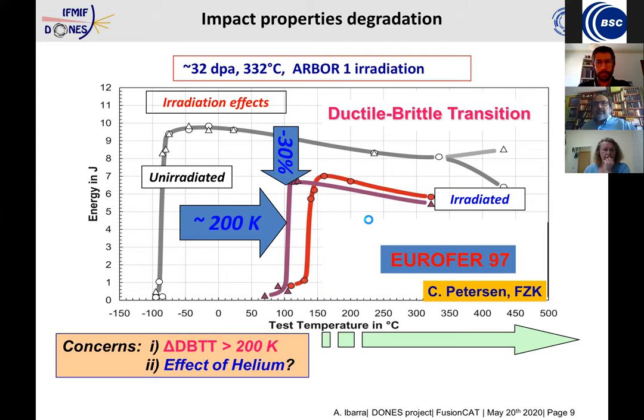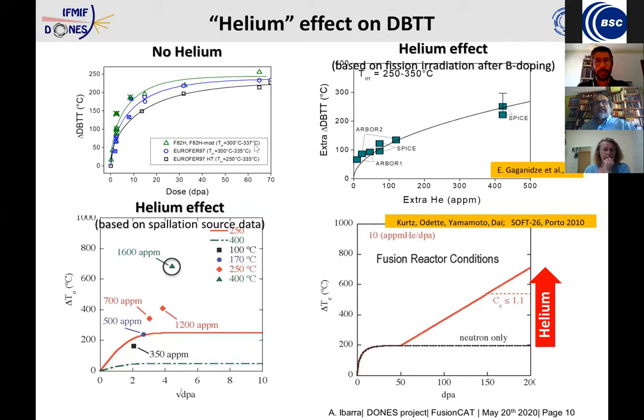This effect happens, and you can see in these figures some qualitative behavior of it. The shift of this temperature is up to 200 degrees centigrade as a function of the irradiation dose, even in the case of no fusion reaction. The experiments in the left part of the slide are made in fission reactors. So that means that this behavior happens just because we have defects in the material. We do not have a very clear idea of the behavior if, besides this, we have helium or hydrogen in the material.